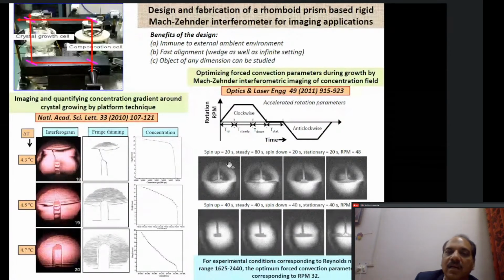So we followed this mechanism of forced rotation, and then using our interferometric techniques, we were able to find out what should be the values of times for which it should be accelerated, it should be constant, then it should be decelerated, and then it should be stopped. And we mapped the concentration fields continuously during the different parameters of our experiment, and we were able to show the optimized values of these: T up, time steady, time down, time stationary, and also the rotation rate. What RPMs should we use so that we get a uniform concentration field around the growing crystal, because that is what is desired. That is what will give us a uniform growth rate and also good quality crystal.